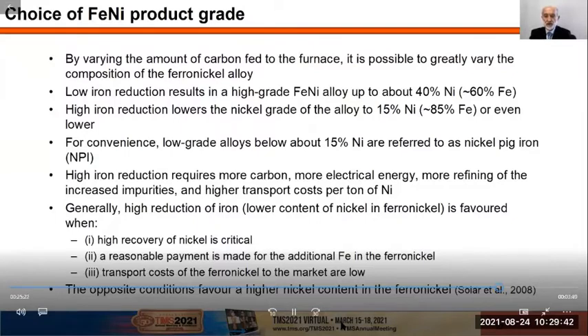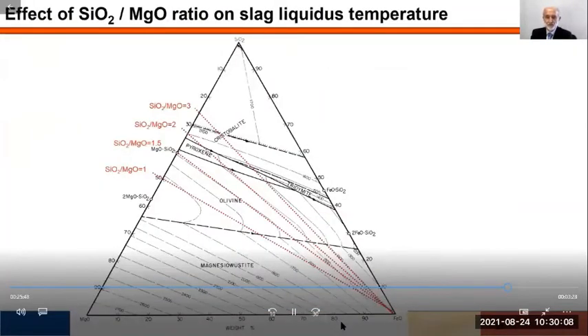Generally, high reduction of iron, that is, a lower content of nickel in ferronickel, is favored when high recovery of nickel is critical, as in the case of a custom smelter, and a reasonable payment is made for the additional iron in the ferronickel, and transport costs of the ferronickel to the market are low. The opposite conditions favor a higher nickel content in the ferronickel.